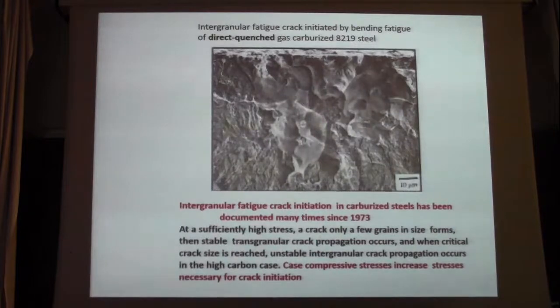You still get intergranular fracture on these carburized steels, but at very high stress levels that are required because of the compressive stresses introduced by the formation of the martensite. Now, the distribution of the residual stresses, the compressive stresses, are high at the surface, and then they decrease, and there's a transition at the carburized case in the core, and sometimes fracture occurs there, at lower stresses than the intergranular fracture because of these favorable compressive stresses.